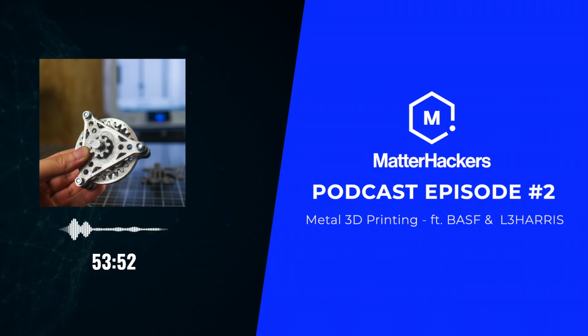So while a first layer is important for every print, it's particularly important for the BASF stuff because it gives you the first look at whether or not you're extruding properly. If you see any little voids or gaps between your first layer lines, chances are you're setting yourself up for failure down the road. In terms of difficulties, it's pretty standard in terms of what you're looking for.